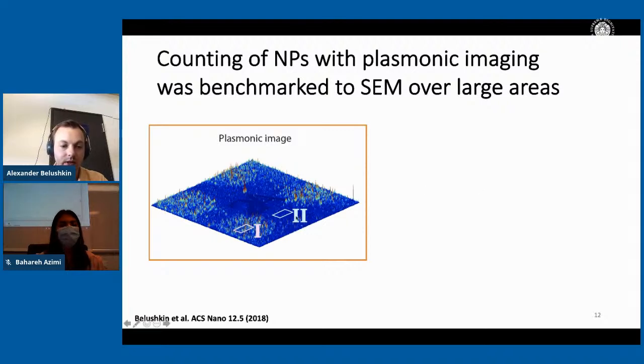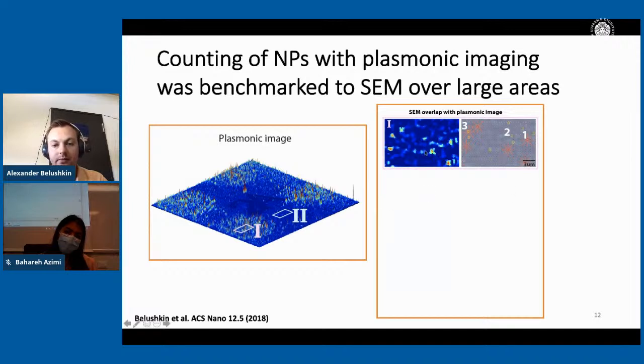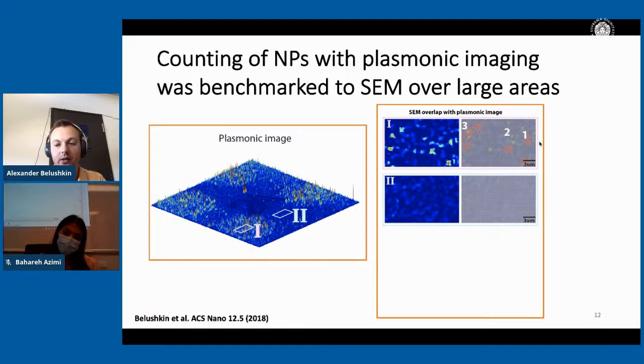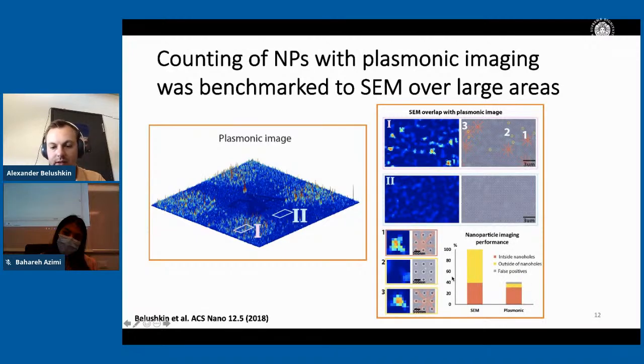You can see here areas 1 and 2. Area 1 is on the spot where you have nanoparticles bound, and area 2 is just a negative background control without any nanoparticles, just to check. You can see here with the nanoparticles we have 3 bright spikes, which also correspond to nanoparticles that bind inside of the nanoholes, while at the background we basically have nothing. We repeated that time and time again over different chips, in a lot of different experiments, and in total we counted over 1,000 different nanoparticles. What we can see is that about 40% of particles bind inside the nanoholes on the SEM.